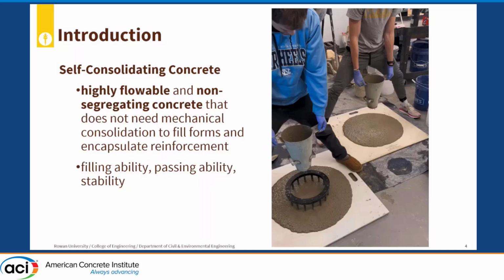To say that your SCC has excellent filling ability, the spread diameter with J-ring flow should be similar to the diameter without the J-ring. We can achieve these excellent properties by maintaining low dynamic yield stress and sufficient plastic viscosity to prevent segregation.